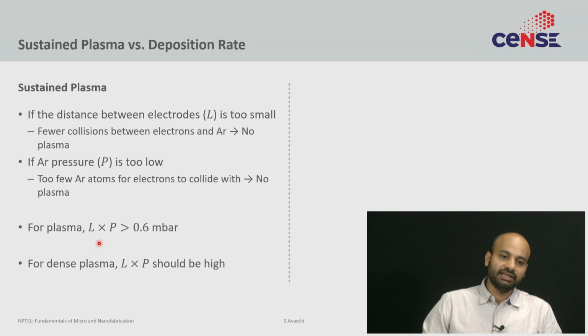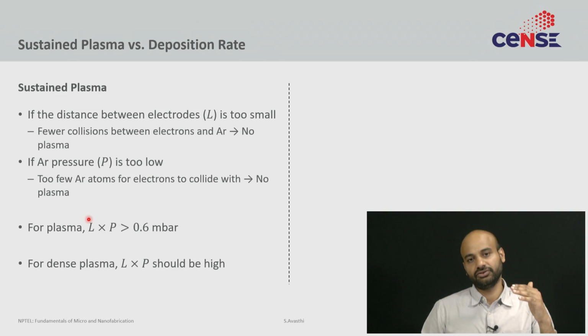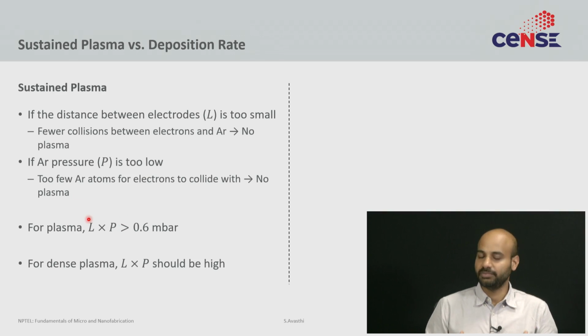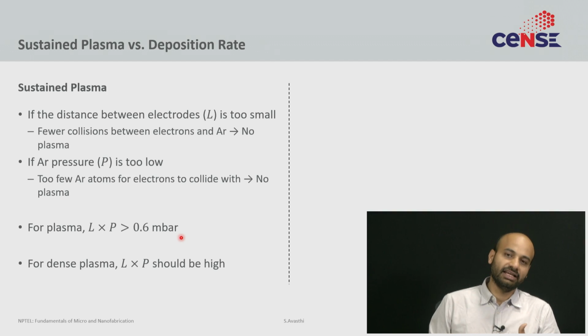Overall, you can say that, for plasma to occur, you need a certain product of L cross P. You need a certain electrode to electrode distance and you need a certain amount of pressure. Empirically, that number turns out to be L cross P must be more than 0.6 millibar. Now, I think millibar centimeters maybe. And now for dense plasma, the higher the L cross P product, the more dense the plasma.